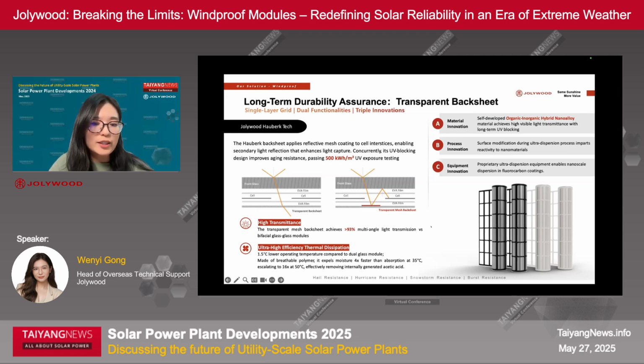This glass-backsheet structure can also provide ultra high efficiency of thermal dissipation. It's kind of a breathable polymer solution that can provide much better temperature performance. It can remove the internally generated acetic acid, and also help to improve the temperature coefficient and many other important temperature characteristics.